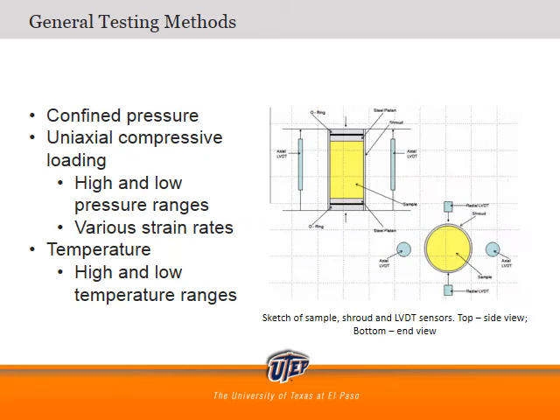The testing specimens will be under confined pressure as well as subjected to uniaxial compressive loadings. These loadings will range from high and low pressure ranges, and they will be applied at various strain rates. The specimens will also be subjected to high and low temperature ranges at these loadings.